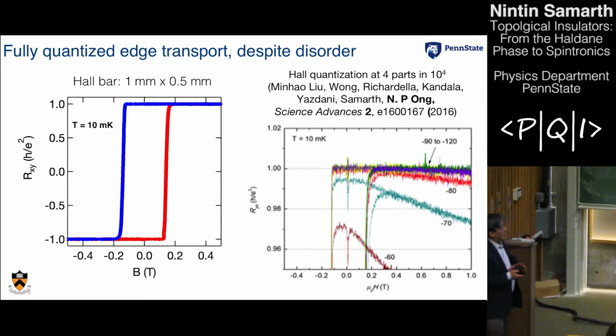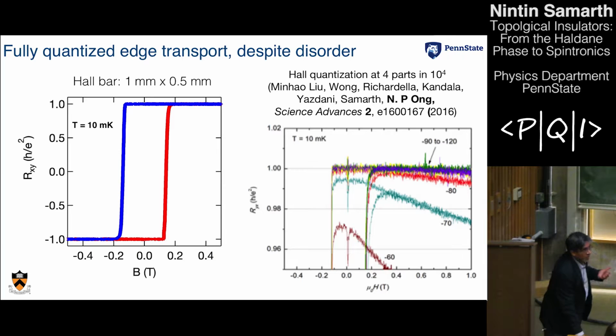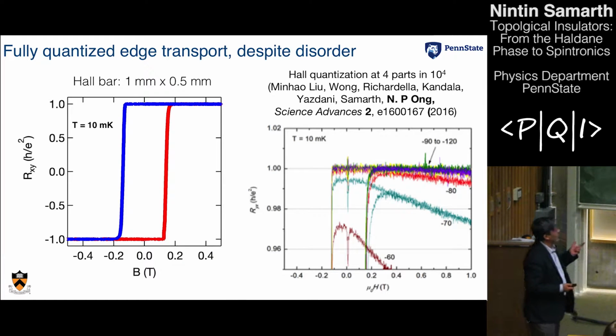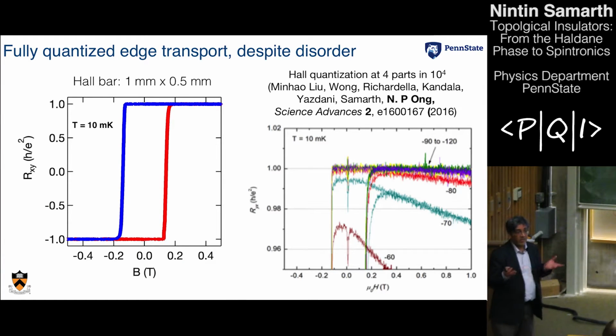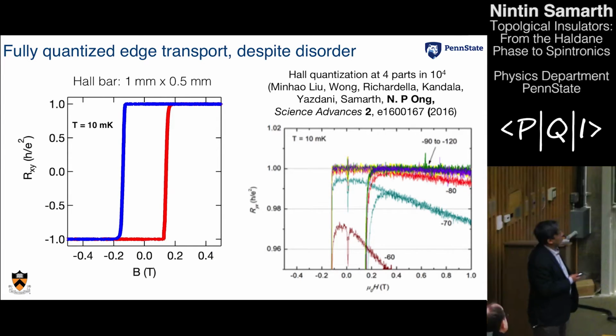So despite the fact that you have these samples with structural defects, the electronic disorder is also quite high. The mean free paths are typically only about 30 nanometers or 50 nanometers, somewhere thereabouts. If you go to very low temperatures, we find that the quantization of Rxy is extremely precise, 4 parts in 10 to the 4. So despite the presence of all this disorder, you can precisely quantize the phenomena associated with these edge states.